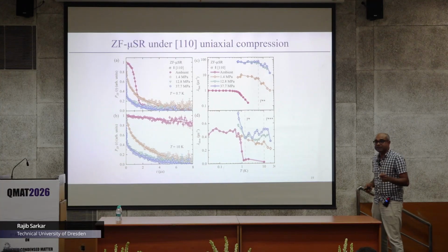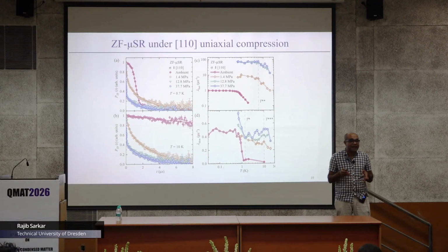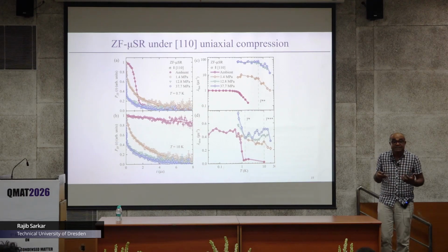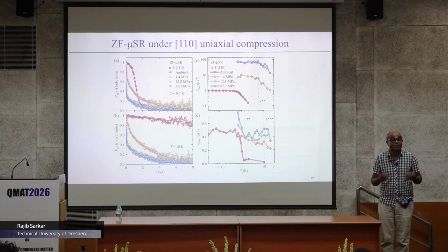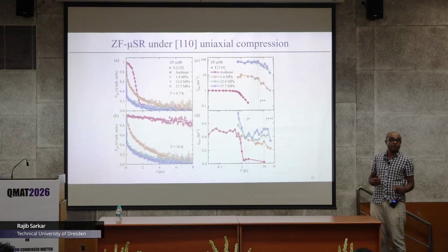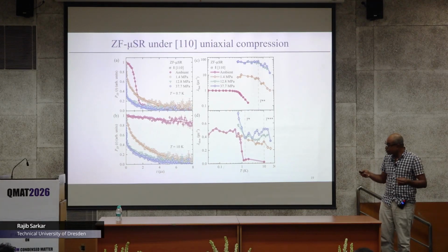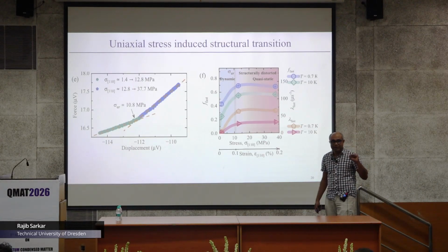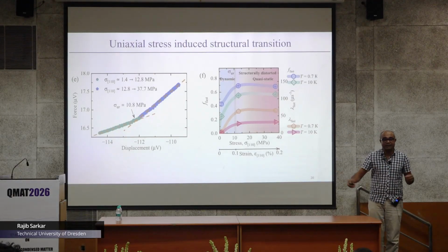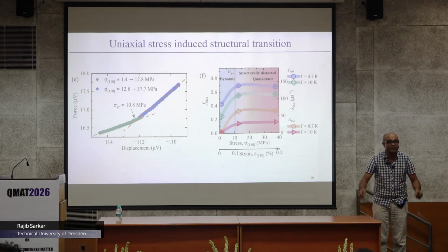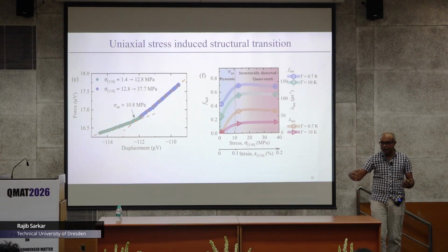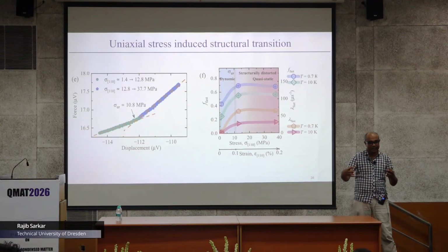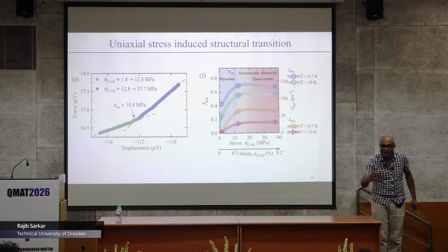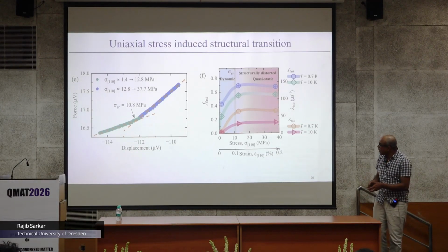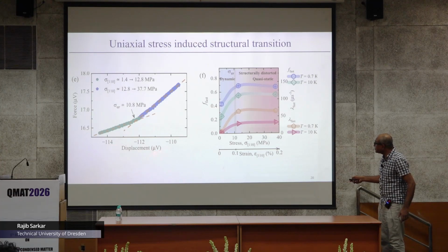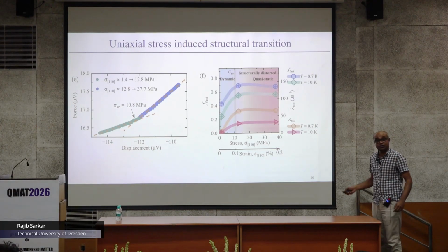Okay, now the question is where are these things actually coming from? And are my systems really homogeneous, or is there something happening to my crystalline symmetry? That also you can find out by the same measurements. So what you have to do for that, this is a simple measurement. When you are doing these measurements, you basically apply the pressure to your system. How do you do it? You have 4 piezos, you apply an external voltage, okay, and that voltage basically makes a displacement to your system, right, to your sample. And now this is basically my displacement, which is in microvolt, and this is my force, which is also in microvolt.